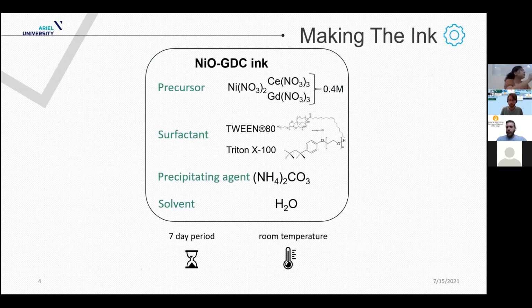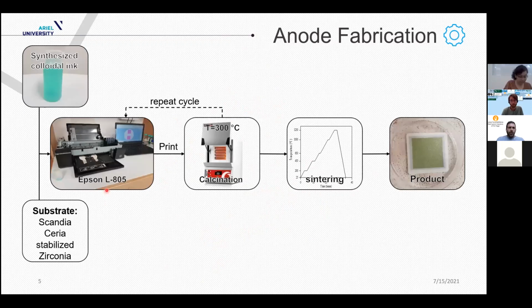Okay, so for the synthesis of the ink, I used nitrate salts for nickel, cerium, and gadolinium, and surface active agents to maintain uniform particle size over time. I chose ammonium carbonate as the precipitating agent and water as the solvent. After mixing all the components for 7 days at room temperature, the ink was ready to use. The fabrication process was to synthesize the ink, load it on a printer, and calcinate after each cycle. Afterwards, the sample was sintered at 1200 degrees Celsius to achieve the final product, which was the nickel GDC anode on the ceramic electrolyte.